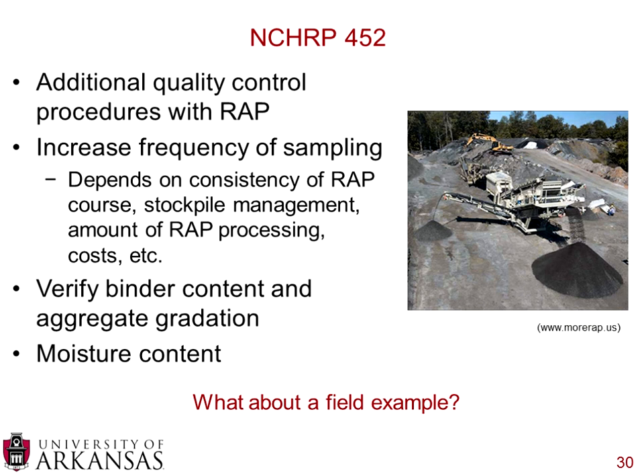NCHRP 452, the number's a little lower, so it came out actually before 752, and they also talked a lot about quality control procedures. Here in this report, they actually suggested you increase your frequency of sampling compared to traditional virgin aggregate. So you can see even within NCHRP, there's not 100% consensus on how to properly manage aggregate and aggregate stockpiles. But they do say that the frequency depends on the consistency of the RAP, how you're managing the stockpile, the amount of RAP you're processing, and the cost of that sampling, all those types of things as well.